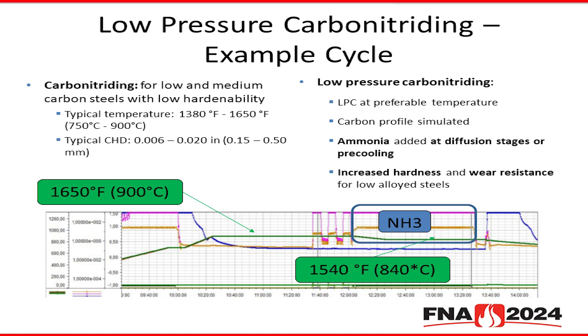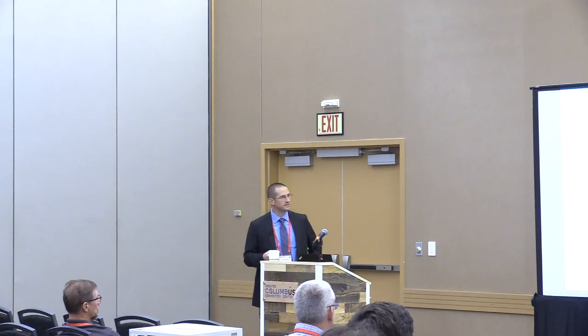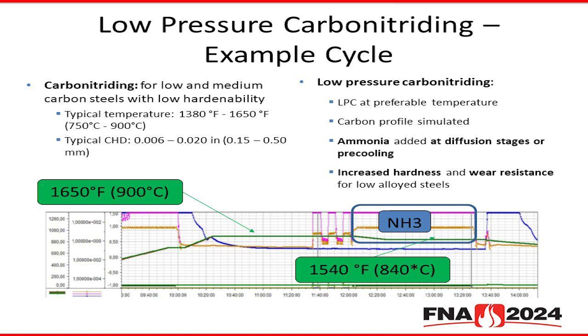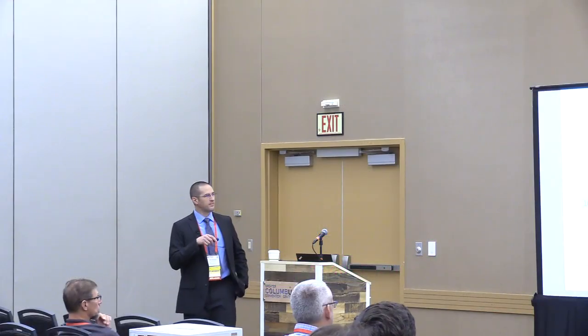Now, that being said, moving on to a hypothetical example of using LPCN. So carbonitriding, typical temperatures, again, for use with low and medium carbon steels with low hardenability. Typical process temperatures are somewhere between 1380 and 1650. In this case, we're going to look at a process that was done around 1650 F, again, in a low pressure carbonitriding scenario where we're adding ammonia during the diffusion stage and pre-cooling.